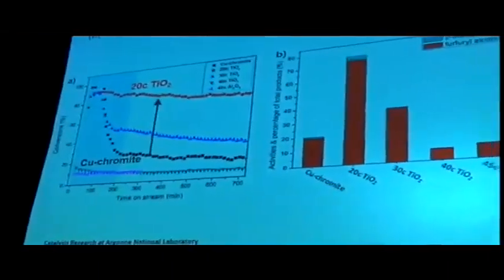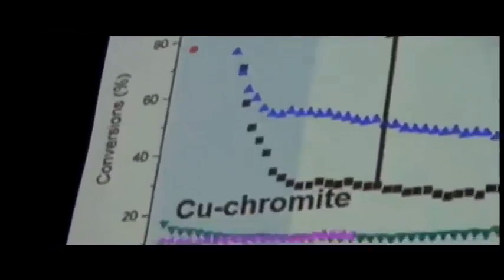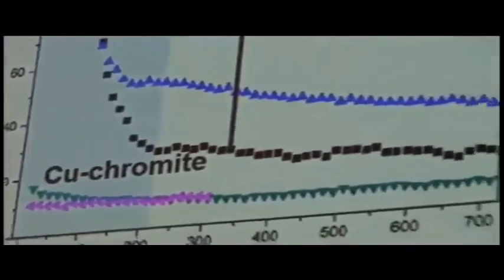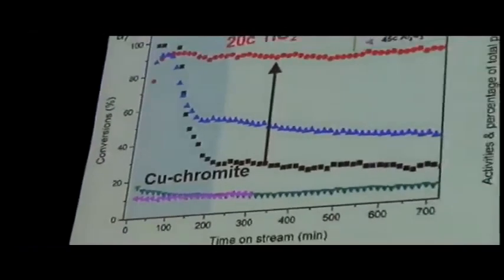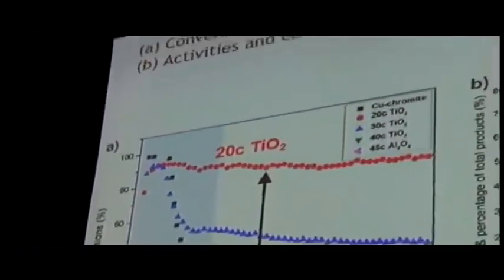So bottom line is, what does it do to the catalytic reaction here? In black on the left, you see the deactivation of the copper chromite that we talked about before. We lose about 80% of the activity in about the first 200 minutes on stream. Okay, you're doing 20 cycles of titania. However, we don't see that deactivation. We see the red curve, which is a lot more active and a lot more stable for time on stream.